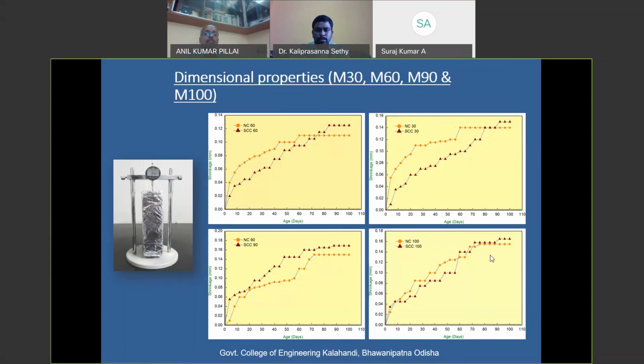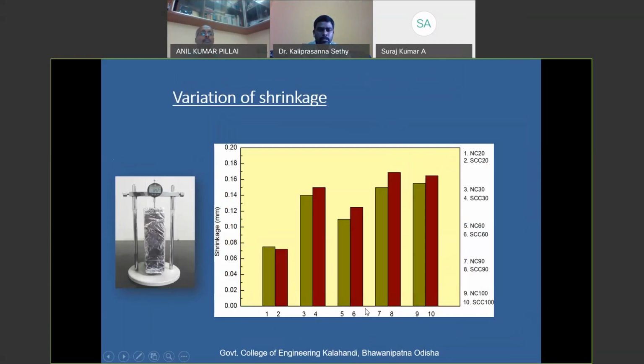So this may be due to the fines content in the high strength concretes which we developed, as we already discussed that the slag which we used here is finer than our cement. So that may be due to that effect. And this is the bar chart of the same values, which you can see for easy understanding. So the maximum shrinkage value we obtained is 0.16 or 0.17.